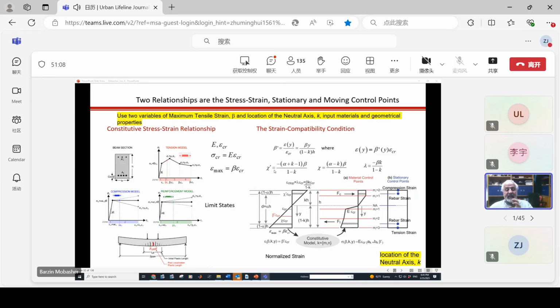What that means is that I can set up these equations, and now I need variables. I need 2 variables. One of the variables is the maximum tensile strain, shown here as beta, and the other variable from here is the parameter K, which is the neutral axis. So if I know beta and if I know K, depending on which zone beta falls, I would know exactly what my strain is in the tension, but then I need an unknown of K, which tells me what my strain distribution is.